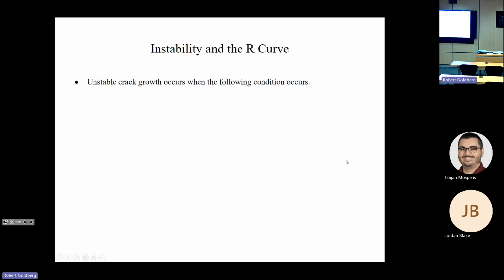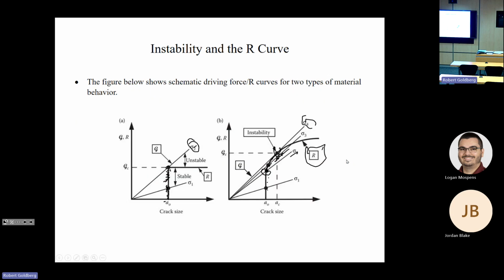And as we talked about, unstable crack growth then occurs when the rate of increase of your driving force, the strain energy release rate, becomes greater than the rate of increase of your resistance. Now, one thing to note is that when your curve is flat, you can unambiguously define your fracture toughness, your critical value of energy release rate. It's very simple. When you hit this particular value of energy release rate, it goes unstable and your crack grows like crazy. So this one is easy. However, for your material with the rising R curve, it's a lot harder to determine uniquely a single toughness value.